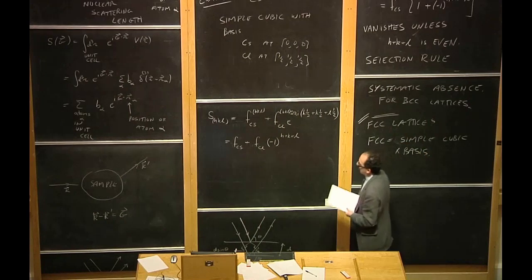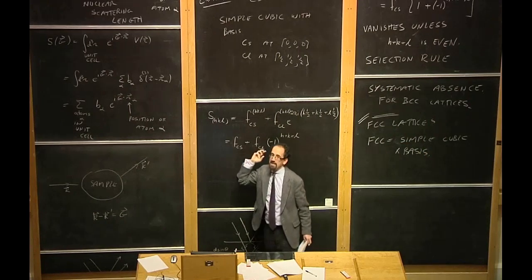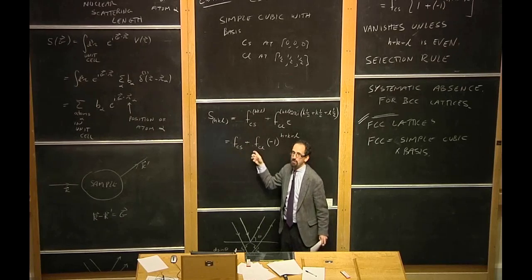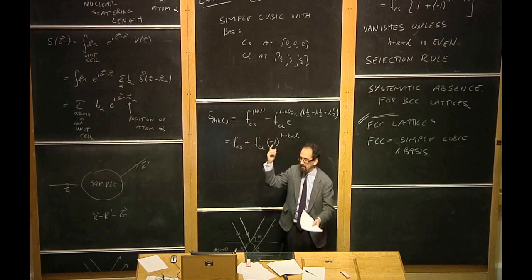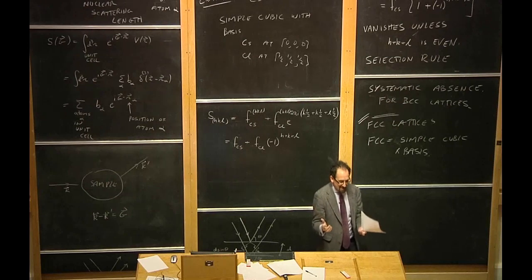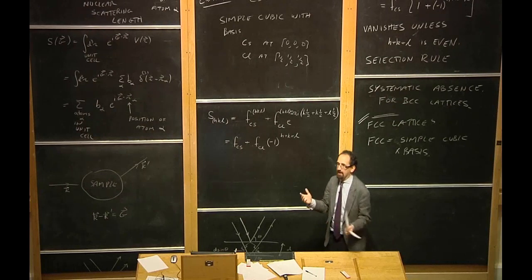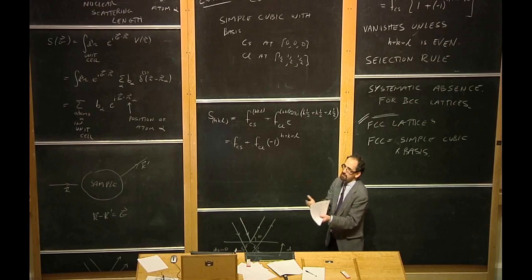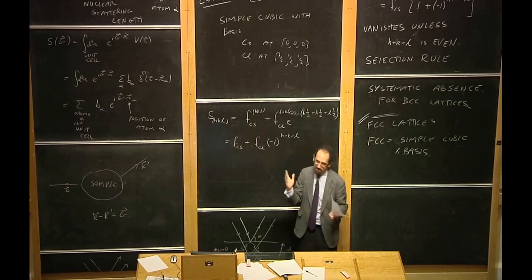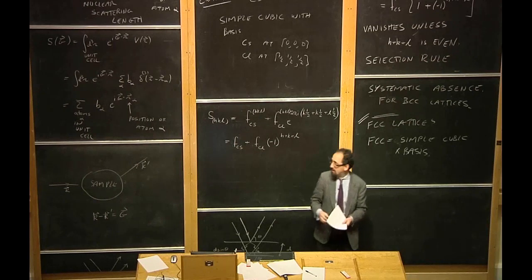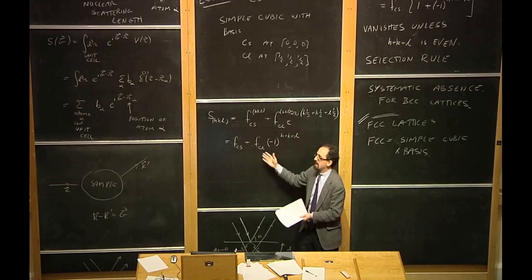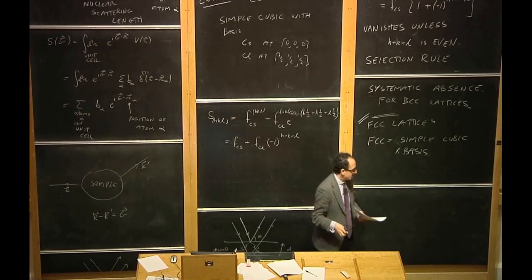Incidentally, I should have mentioned this. If we were looking at nuclear scattering lengths, then there's absolutely no reason you should ever expect any two to be the same, independent of their atomic number. Because you could have a strange coincidence that the scattering length of hydrogen happens to match the scattering length of iron or something crazy like that. But just because they're close to each other in the periodic table doesn't mean that they have close nuclear scattering lengths, completely unrelated. So it's sometimes good if you think there's a near cancellation to switch from X-rays to neutrons, because a near cancellation with X-rays won't be a near cancellation with neutrons generally.